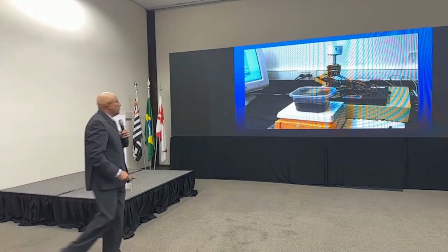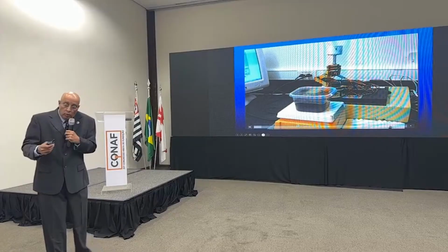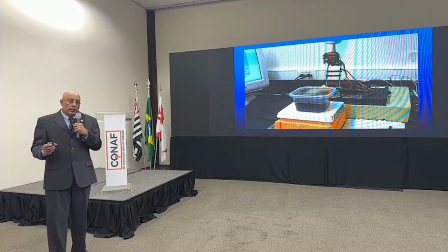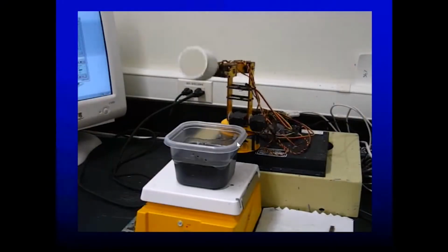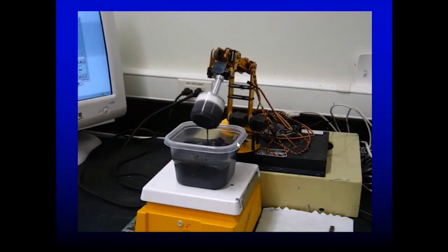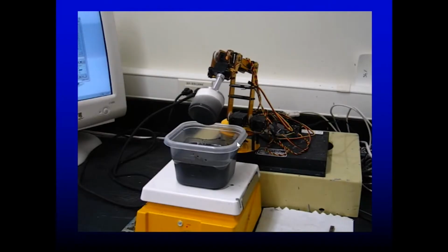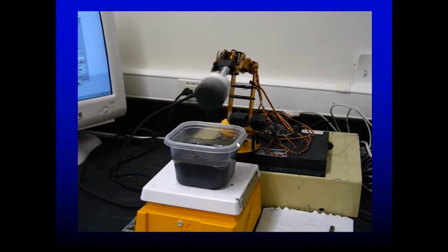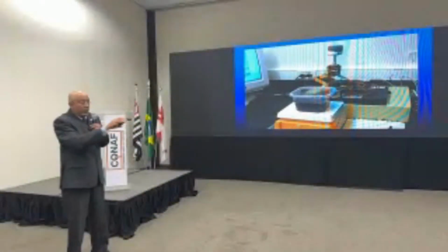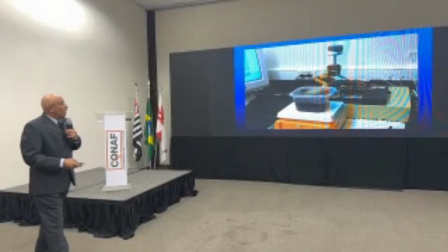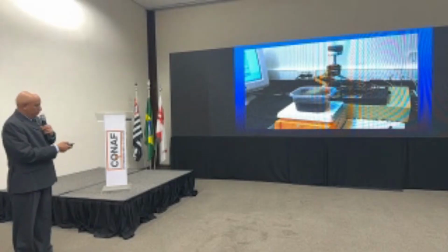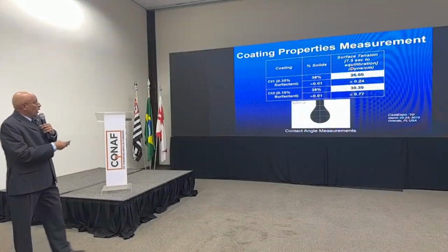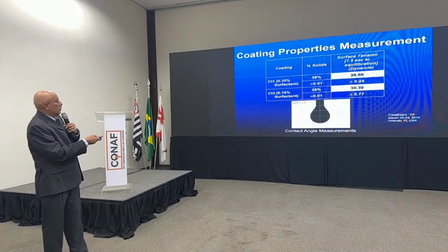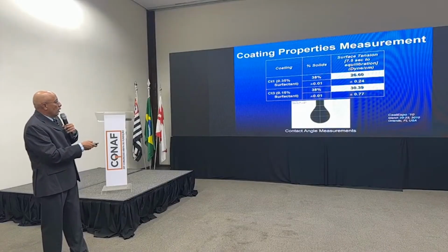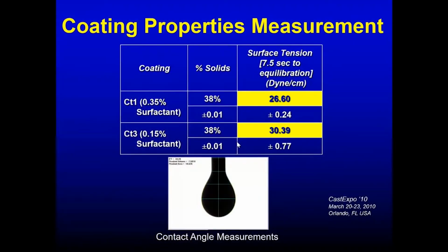So this is how we would study the coating effects, because the coating effects for rheological characteristics of a coating are a function of dip time. And every man shakes differently. So in this case, we have to allow that to be controlled, the wetting and the leveling of the refractory coating to control the level and depth of penetration. We study from the coatings the percent solids, surface tension issues by contact angle measurements. That gives us this data.